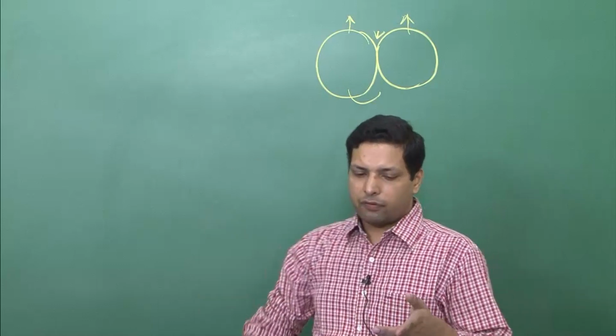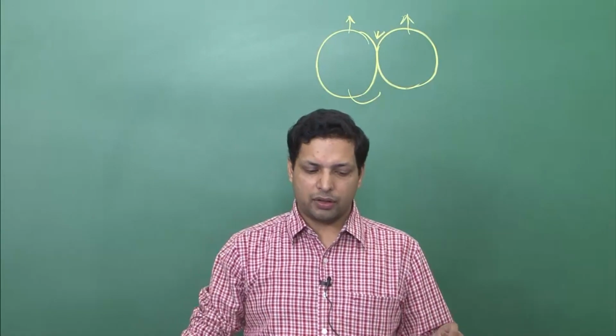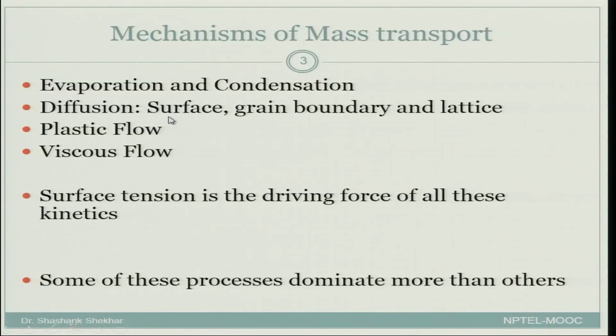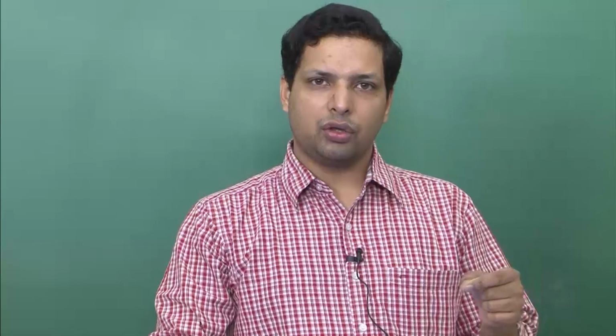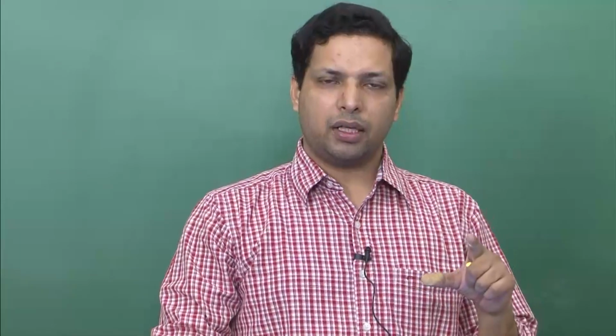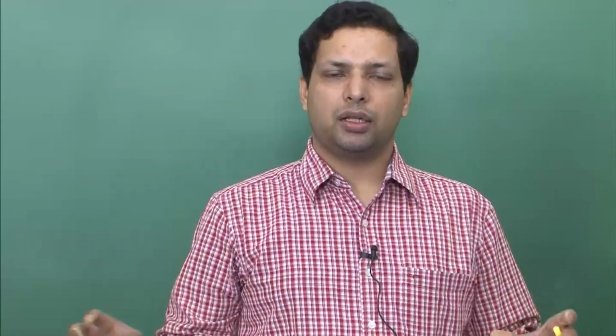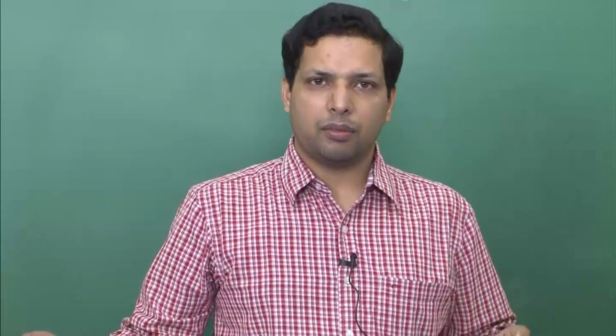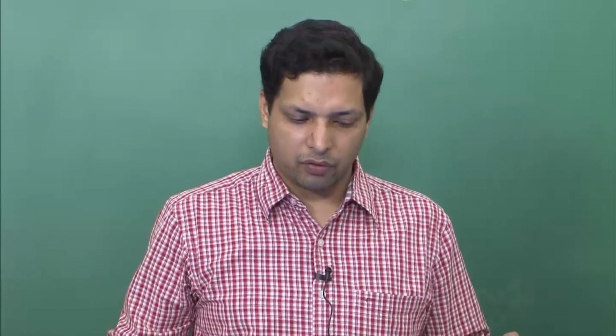and therefore, it will get deposited over here. And similarly, for other mechanisms or other kinetics that we discuss over here, for example, diffusion. We know that several kinds of diffusion, or basically several paths to diffusion exist, and in the case of particulate coalescence, the important ones are surface, grain boundary and lattice. Such diffusion can take place through surface, through grain boundary, and through lattice. All of them in the end allow the mass transport to move from one particle to the neck region. Once the material gets deposited at the neck region and this process goes on, slowly there will be no neck, and in the end, even if there were two different particles, you would see almost one particulate, unless there is a grain boundary getting formed over there.